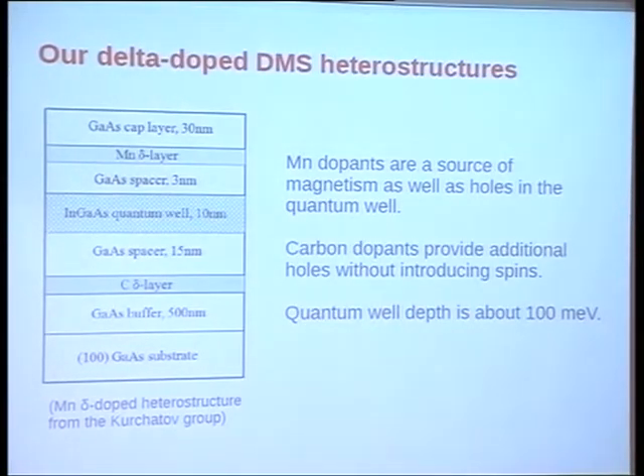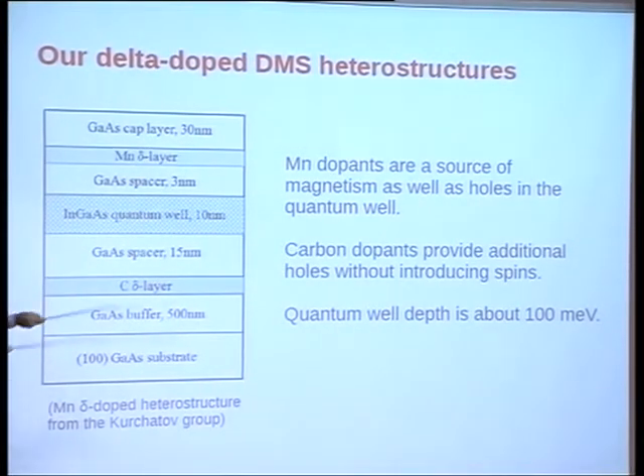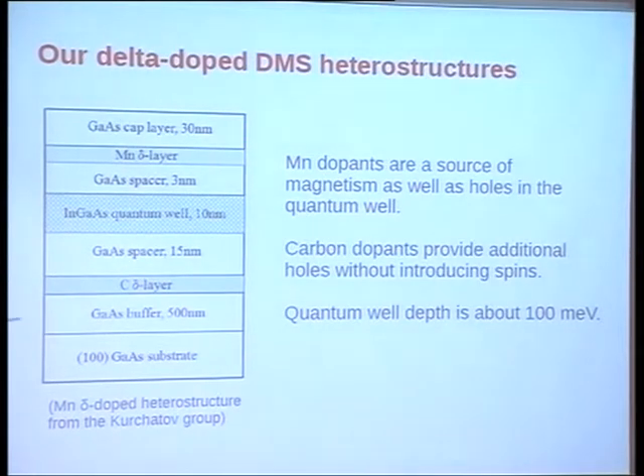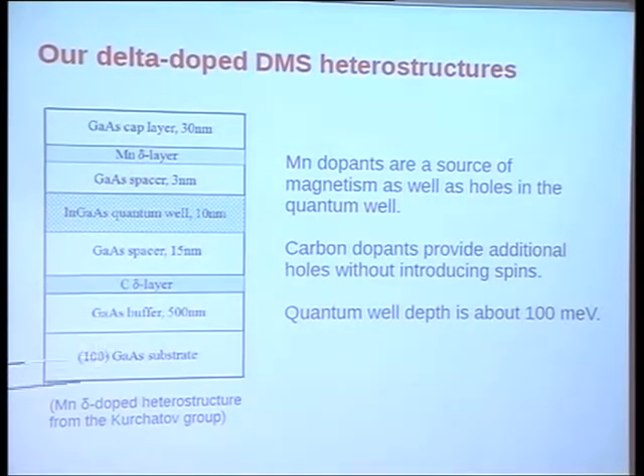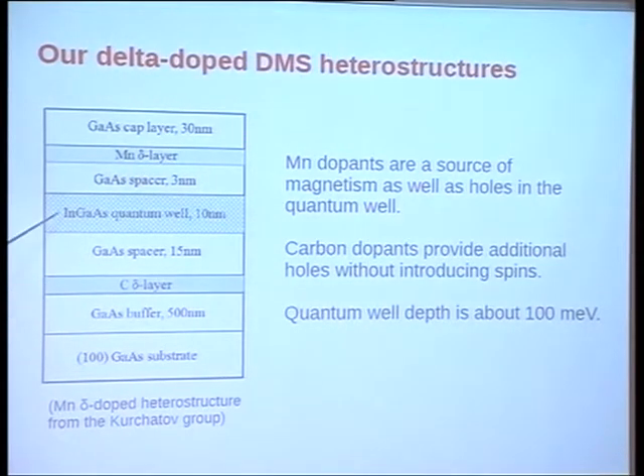Okay, so my collaborators have a way out. They have a different kind of heterostructure. The doping is again in gallium arsenide, but here we have an indium gallium arsenide quantum well, and this separation is comparable to the previous picture I showed by the other groups. The good thing about it, as I'll show you later, is that the two-dimensional hole gas is formed on this side. It has much less overlap with the manganese delta layer. And here I have also got a carbon delta layer, which provides holes without providing any kind of magnetism. So this is kind of a control, or you can use this to give a different background hole density in your quantum well.